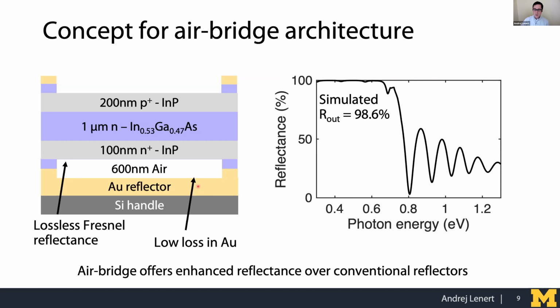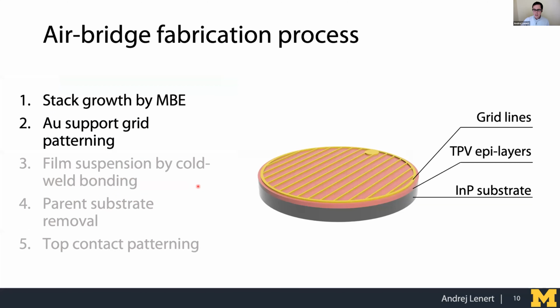And in the next couple of slides, I just want to show you how we achieved the fabrication of this device, how we realized it. And I want to demonstrate that it's relatively straightforward. And I expect that it's something that can be replicated in other labs, or at least I encourage people that it's something that they can accomplish as well. And so I just want to highlight the simplicity of the process for making this air bridge architecture, because there are similar architectures that have been reported, but what was used was a much more complicated process to make them. So we start by growing an epi layer on a lattice matched substrate, indium phosphide, and we define the grid lines that will end up being the supports of the absorber of the air bridge.